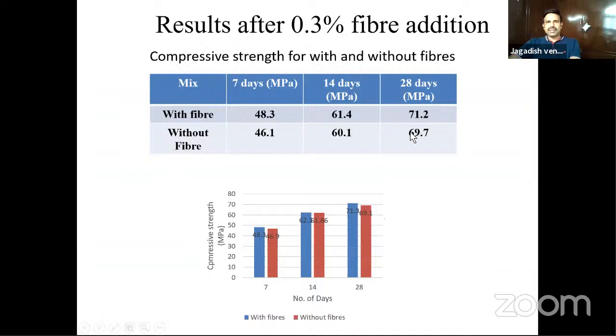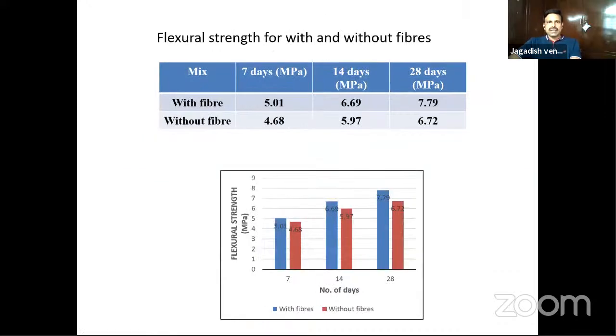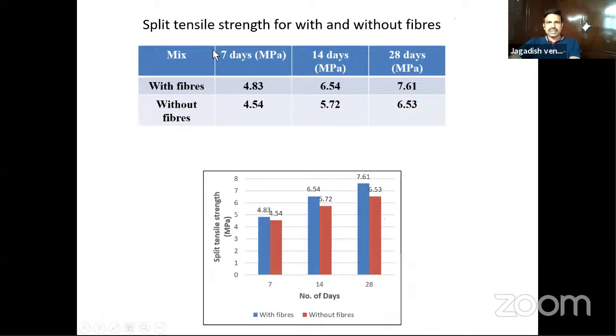This is 0.3 fibers, with and without. In compressive strength it is more or less the same; 1 MPa is not a great difference. And you can see the flexural strength, with fiber we got almost 1 MPa difference. 1 MPa in flexural strength is more. So there is a lot of improvement in flexural strength while using the fibers. Again, with and without fibers, the split tensile strength. Here also you can see the great difference, almost 1 MPa.